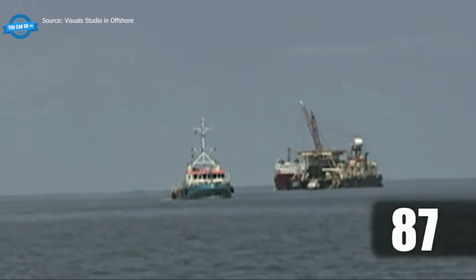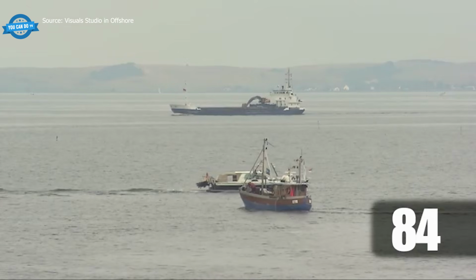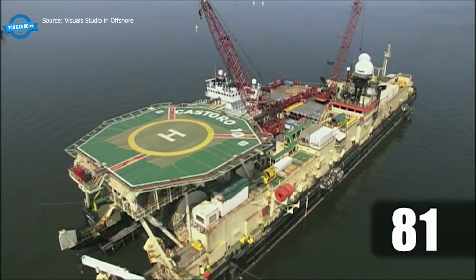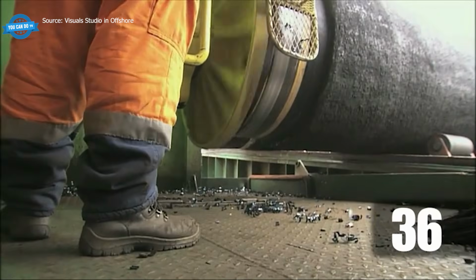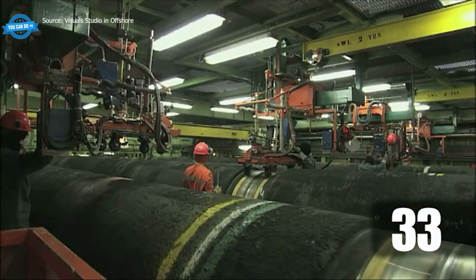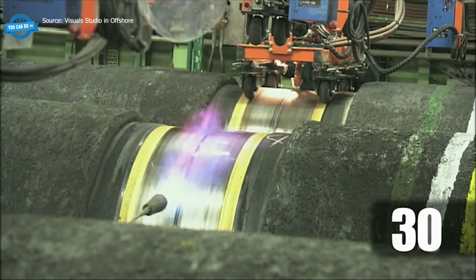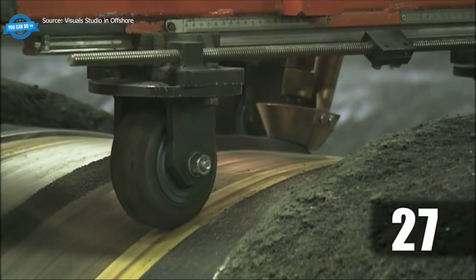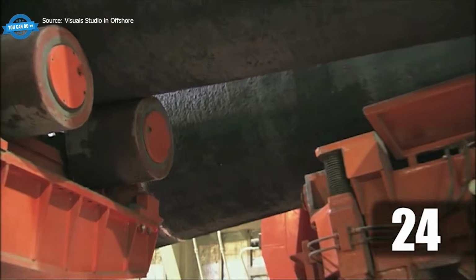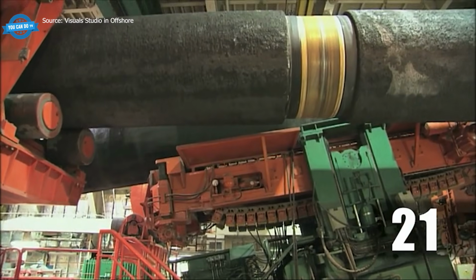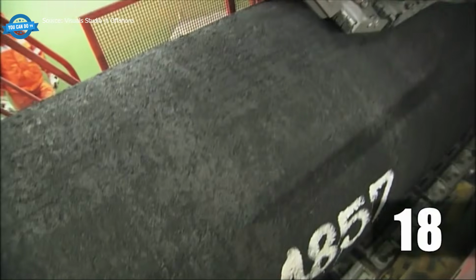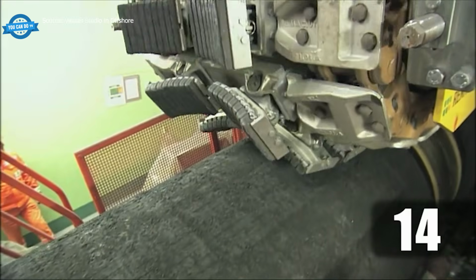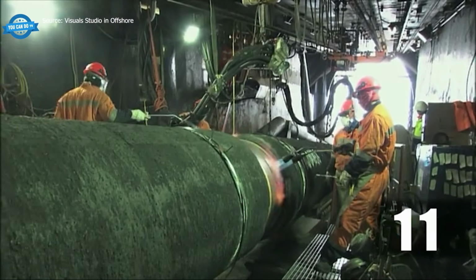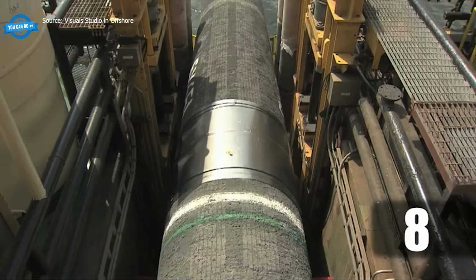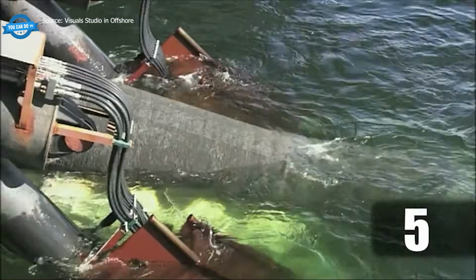The Nord Stream system required 202,000 individual 12-meter pipe sections welded together for a total route length of 1,224 kilometers across the Baltic. Every section had to match the next one for diameter, wall thickness, steel grade, and weld geometry. A single mismatched joint, or one bad section in a chain of 202,000, could shut down the entire line. The logistics alone, coordinating manufacturing, coating, transport, and pipelay, ran across 5 strategic ports.